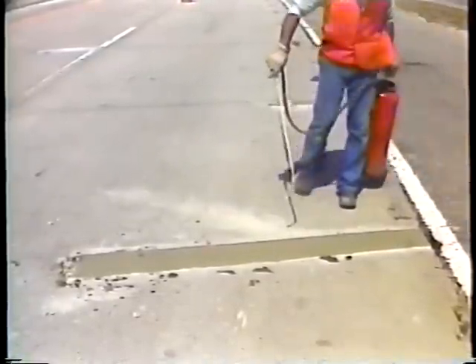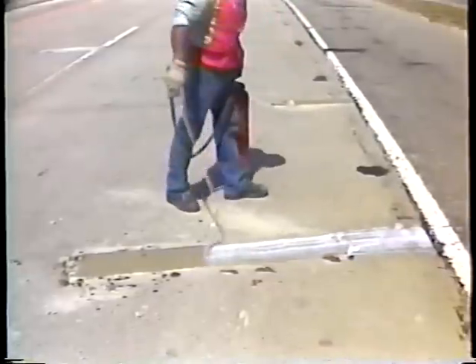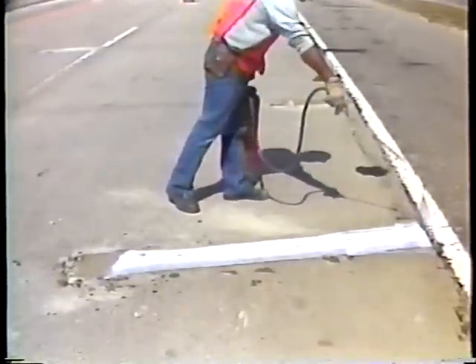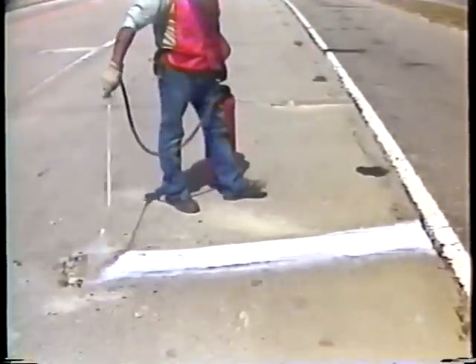After finishing, it's strongly recommended that the edges of the repair be sealed. This can prevent delamination resulting from water seeping at the edges. A 1-to-1 cement water grout provides an excellent moisture seal. Because these small repair areas have a high surface area to volume ratio, they lose moisture rapidly. So proper curing is very important to prevent shrinkage and premature failure.